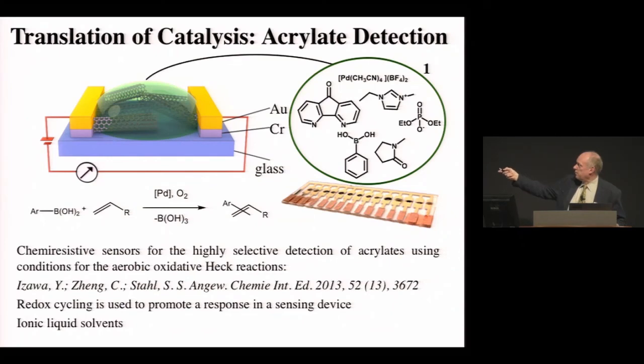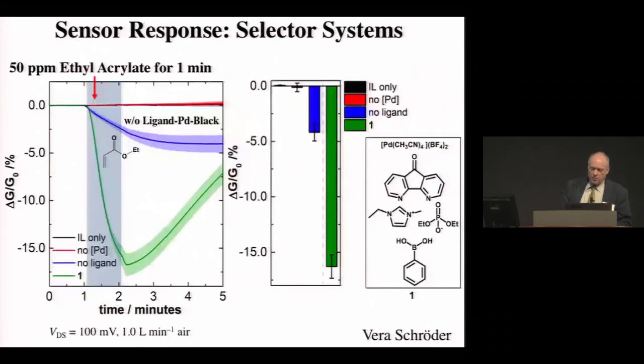So what we did here, this is Shannon's favorite ligand, the one that gives him the highest catalytic rates. It's the thing that binds to the palladium. We have the boronic acid, which is the substrate that's going to basically keep taking the palladium-0 and put it into palladium-2. And then we have an ionic liquid composition. This is a palladium source. And this is just a little solvent that we use to get everything kind of mixed up nicely. So let's see what it does when we put it in our sensor, and it works really quite well.